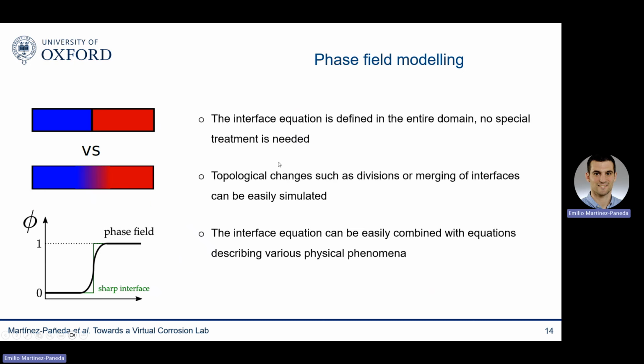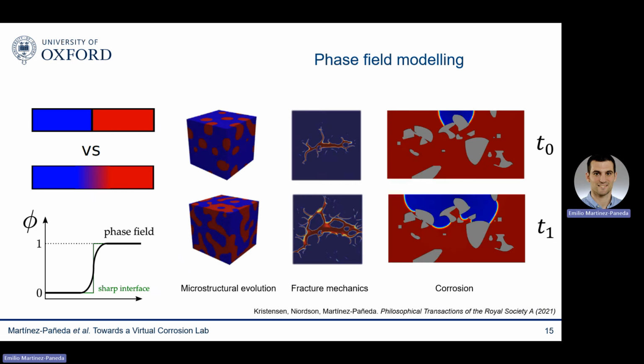And this implicit method of describing interfaces is computationally very powerful, and I'm listing here some of the key advantages. Essentially, you don't have to define those nasty moving boundary conditions. You can capture topological changes, such as the coalescence of multiple pits, in a natural way, and the method is ideal for coupled multiphysics problems. In fact, phase field modeling has been a revolution in many areas of science and engineering. It all started in the condensed matter physics community, where it is now by far the most widely used technique to simulate solidification and microstructural evolution.